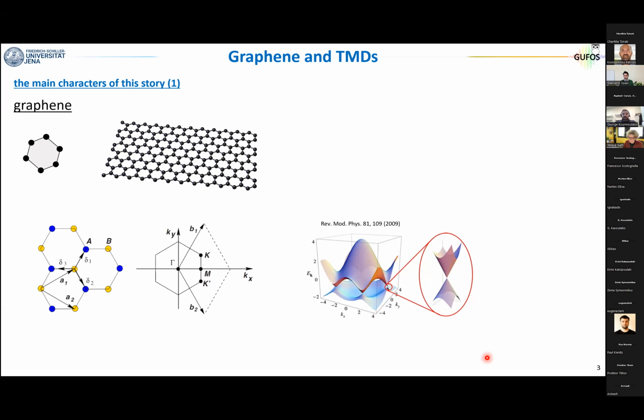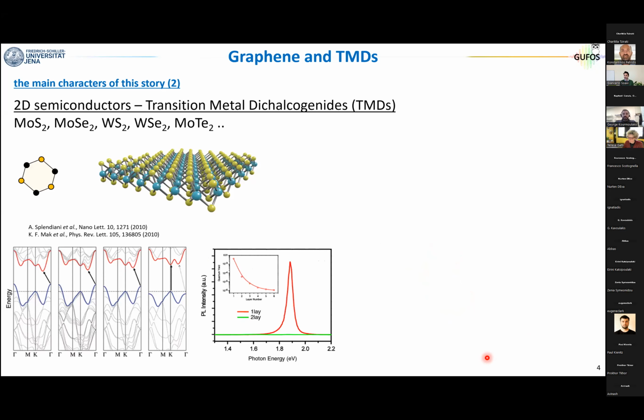But this linear band dispersion will also be very important for us when we do nonlinear optics in graphene. Now, the second main character of this story will be transition metal dichalcogenides. They are again a layered material, but strictly speaking, they are not two-dimensional, because as you see, this time there is a metal atom, typically molybdenum or tungsten, that is sandwiched between two layers of chalcogen atoms.